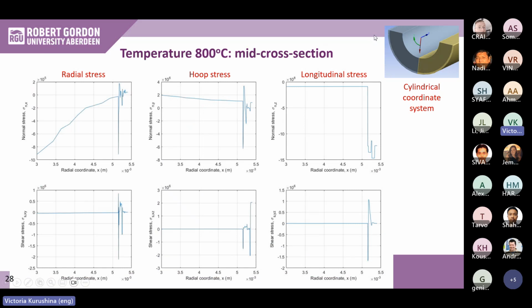So the radial, hoop, and longitudinal stresses are defined using the cylindrical coordinate system, which is placed in one of the fixed ends. If we're talking about the middle cross section, at the 50 millimeters mark for the 100 millimeter pipe, you could also see an exact border for the substrate layer, after which come the functional layers, and we plug into the model only the frictionless behavior in between those layers.